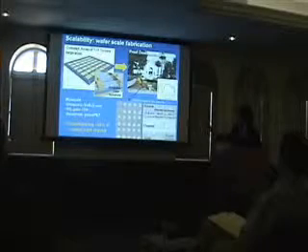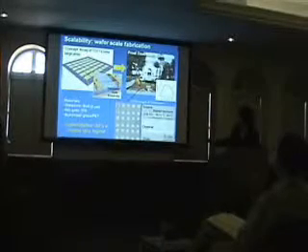Here is the motivation — why do we study transparent electronics? The transmittance of these devices is about 85% in the visible light regime. When we zoom in, we can see several devices. This is the source, this is the drain, and this is the channel. Here is the zoom-in of the channel part, and you can see aligned nanotubes bridging between the source and the drain. What's notable is the nanotubes are still aligned even after complete fabrication, as we expected.